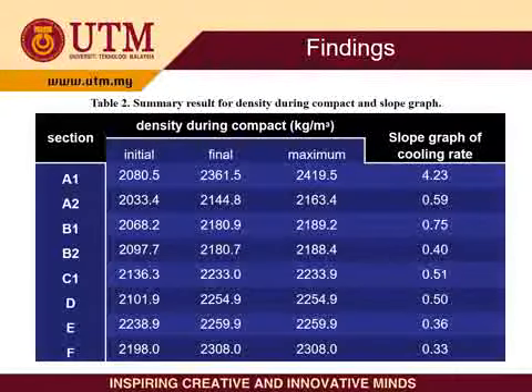For findings, table 2 shows that WMA premix achieves higher maximum density during compaction compared to HMA premix. Concurrently, WMA has a smaller slope graph of cooling rate than HMA. It can be summarized that the temperature of WMA mixture decreases slowly but still provides higher density that keeps increasing. It is different with HMA, where the slope of the graph is higher because the temperature of HMA mixture decreases quickly, but when the compaction is completed, the density achieved decreases. In a nutshell, WMA mixture provides better cooling rate during compaction and higher density compared to HMA.